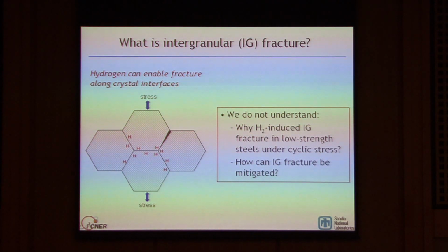So what can happen, especially in the presence of hydrogen, is that hydrogen can segregate to these grain boundaries. One hypothesis is that hydrogen weakens the bonding across these grain boundaries, and cracks can form there. This is at least an accepted hypothesis for why we get cracks along grain boundaries in the presence of hydrogen.